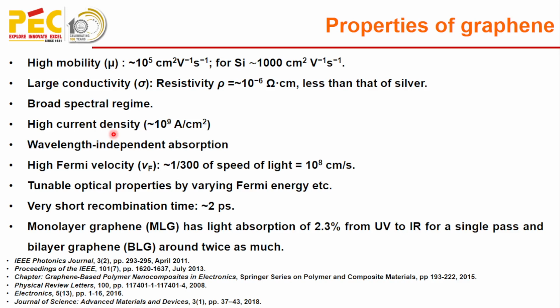It has wavelength independent absorption. It has a high Fermi velocity, which is of the order of 1 by 300 times the speed of light. It has tunable optical properties by varying the Fermi energy. It has a very short recombination time, around 2 picoseconds, and monolayer graphene has light absorption of 2.3% from ultraviolet to IR for a single pass, and bilayer graphene has twice as much.